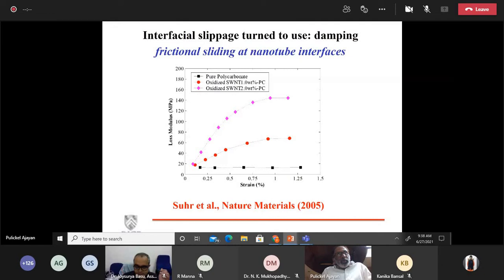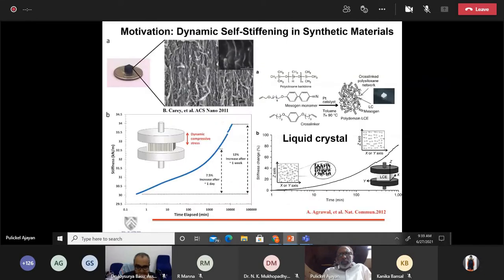Now, the reason why in nanocomposites the interfaces are so impactful is, as I said, the large volume of these interfaces and how this huge interface volume can be changed by changing the way these are engineered. A perfect example of something like this is an experiment we did with nanotubes and polymers a while ago. What we saw was that under dynamic compressive loading, the material actually self-stiffens, because during this high strain loading, the interface keeps changing continuously. That's very unique, because self-stiffening materials would be very useful for many technologies. So using this idea of large interface volume in nanocomposites, one could play around and see what kind of properties can be controlled and what kind of new emerging behavior can be introduced.